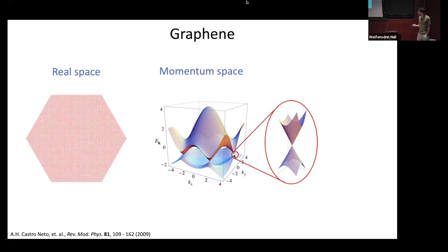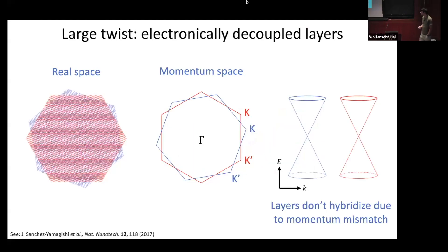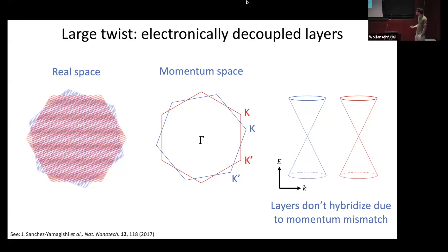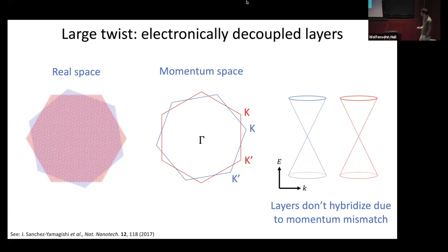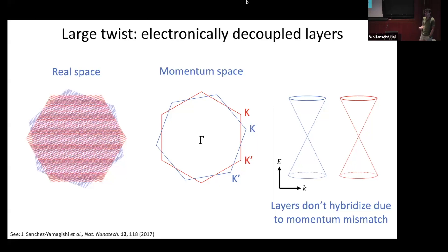To build upon this, consider two limiting cases with two different layers twisted relative to one another. First, if you have a large twist angle, in momentum space the Brillouin zones are twisted relative to one another. If the twist angle is very large, the low-energy electronic states at the K and K' points in each layer are very far separated in momentum. Therefore, up to fairly large energies, these two Dirac cones don't hybridize — you get two electrically decoupled systems that can be independently tuned with an applied electric field.